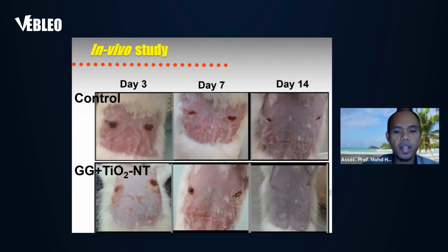The specialty of the biofilm is that it will degrade by itself during the healing, and then the wound will be recovered almost 100% after 14 days. At the same time, we cannot see any scar left on the rat. So we can conclude that our biofilm is not only capable of healing the wound, but at the same time can remove the scar of the wound. That is the specialty of the Gellan gum GG incorporating titanium dioxide nanotube biofilm.